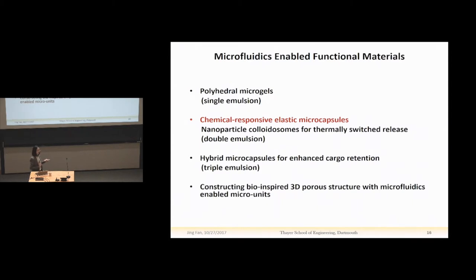We first of all want to prove this concept. So we need to make microcapsules with precisely controllable geometry, for example the shell thickness and the size of the capsule, and also the components, for example the concentration of the surfactant in the core. And then we inject these smart capsules into a model porous media system and examine their transport behavior and also examine the oil recovery efficacy using these capsules. So this is what we did.